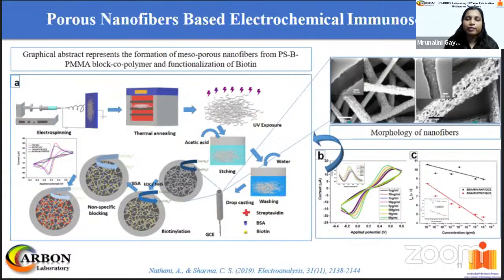For this, we first activated the specific binding site by using EDC NHS chemistry. The biofunctionalization of biotin was carried out by treating the surface of nanofibers with biotin hydrazide solution. And then non-specific sites were covered with BSA. When the immunosensing was carried out, it was found that the mesoporous nanofibers increased the sensitivity of streptavidin detection to 6-fold. Thus, we employed a 3-step process to separate a polymer phase from block copolymer and obtain controlled nanoporous and mesoporous morphology, which can be utilized in a wide array of sensing.